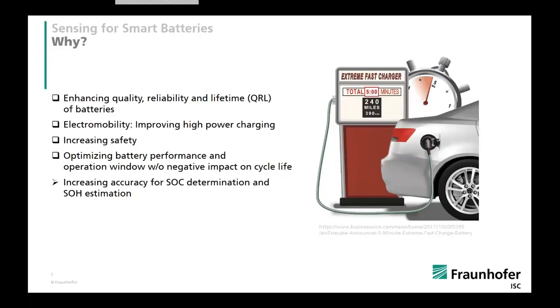And if high power charging in a few minutes was not difficult enough, the real trick is to optimize these properties without negative impact on cycle life. You all know it. If you charge your battery very rapidly, the anode potential will drop below the limit where certain effects happen, like lithium plating and so on. And this is what we want to prevent, of course.